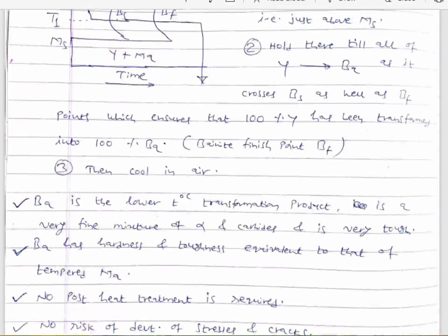Bainite is the lower temperature transformation product. It is a very fine mixture of ferrite and cementite or ferrite and carbides, and it is very tough. Bainite has hardness and toughness equivalent to that of tempered martensite. So when the hardness and toughness is equivalent to that of tempered martensite, then why should we take that much risk in hardening by quenching if your aim is fulfilled by this single heat treatment? Moreover, no post heat treatment is required. Post heat treatment means like tempering. Tempering is necessary after hardening by quenching to relieve the internal stresses, to convert the brittleness of martensite into tough tempered martensite, to convert the retained austenite into either bainite or martensite.